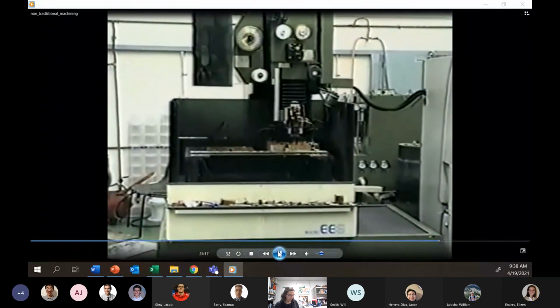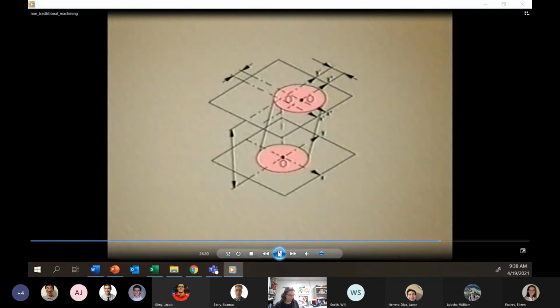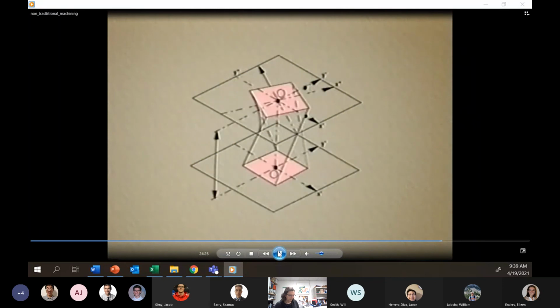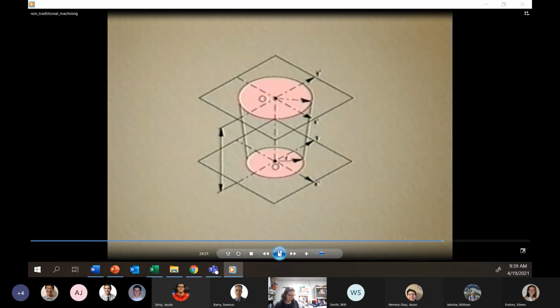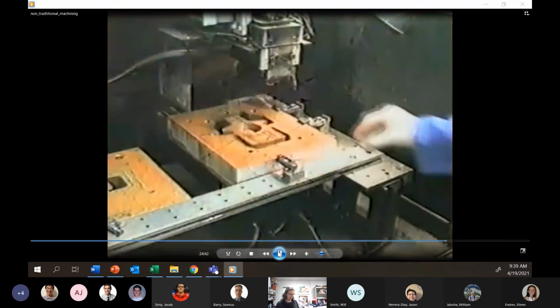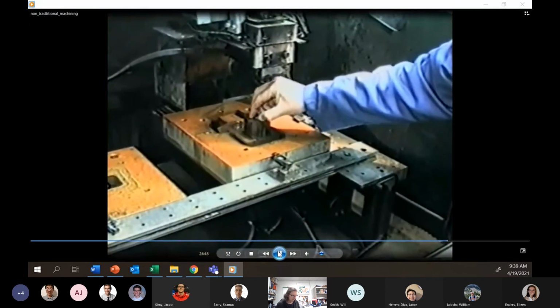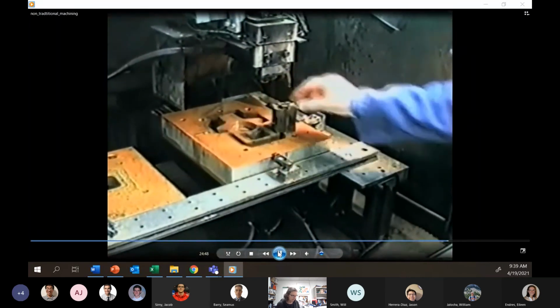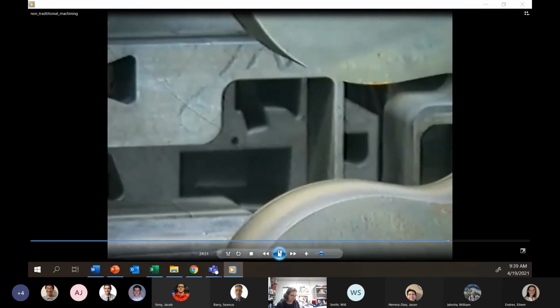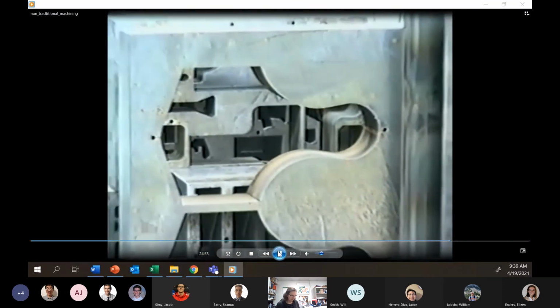The work moves in the XY direction relative to the wire. With CNC controllers, it is possible to angle the wire so as to offset the top shape from the bottom shape, or rotate the top shape relative to the bottom shape, or scale the top shape to the bottom shape. This is particularly advantageous when making a punch and die, as the larger top face of the punch can be made to fit the smaller hole on the bottom, thus making the punch and die from the same piece of metal. The shapes that can be produced are limitless.